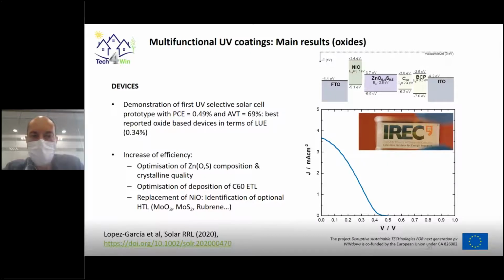For this, we are working on the optimization of the composition of the absorber layer, so we might reduce the band gap a bit to increase the efficiency. And we also need to improve the crystalline quality of the layers to increase the grain size.